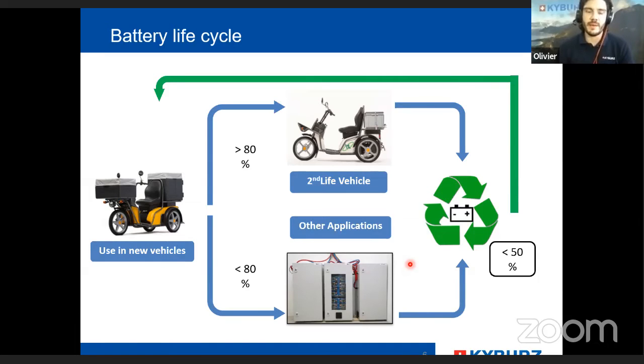And if we look closer at the life cycle of the battery, we take it apart and make new capacity tests, and we saw that about 60% of all the batteries used in 2009 have a remaining capacity of over 80%. So the state of health is over 80%. This means we give them a new life in the second-life vehicle. The other 40% have a capacity of 70 to 80%, and with these we are now building energy storage systems. And once the battery has a state of health lower than 50%, we recycle the batteries.